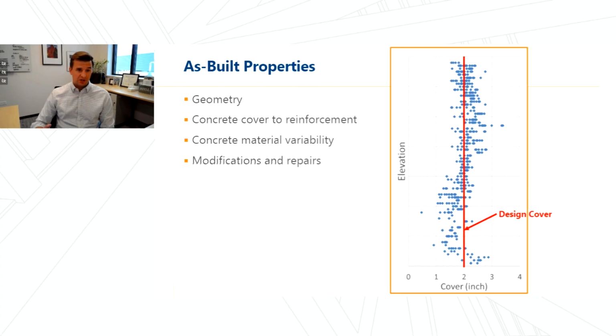It's also, for concrete structures, reasonable to expect variability within the structure. That is, variability of the concrete material, especially if it's a large asset that was built over some considerable period of time. For example, we've seen structures that are 1980s vintage that have reactive aggregates, and the mitigating benefits of fly ash were incorporated into the design, but we might see a wide distribution of fly ash present in sampled material, including areas that didn't have any evidence of fly ash. And we also have to recognize that these assets serve an operational purpose, and they are intended to stay functional and operational. And so over the history of a structure, there may be a number of modifications and repairs. The extent to which those are documented might vary considerably.